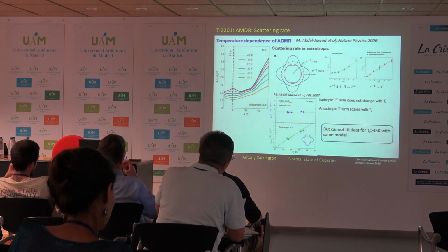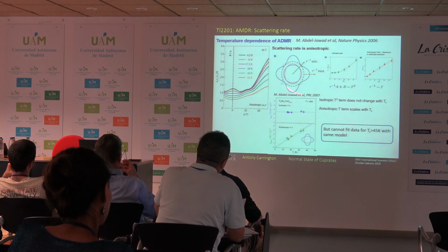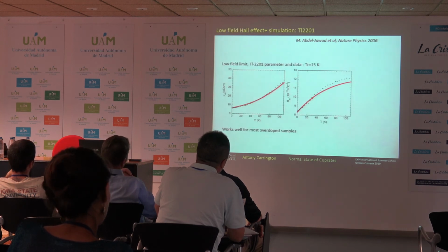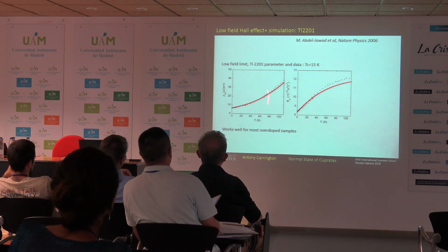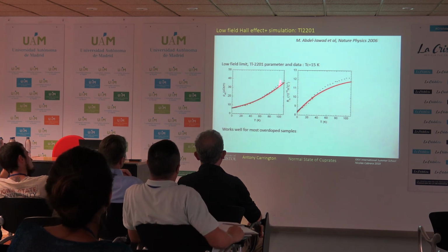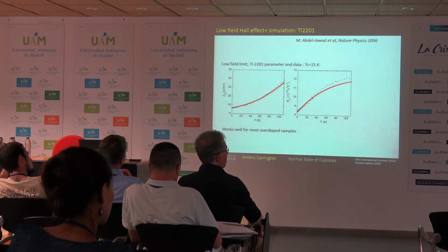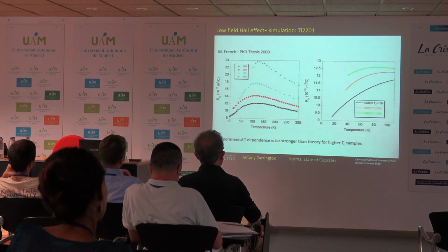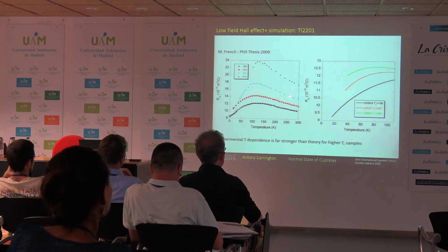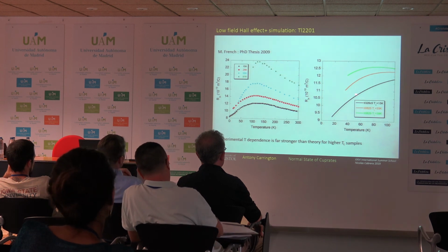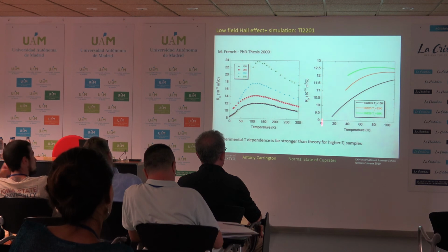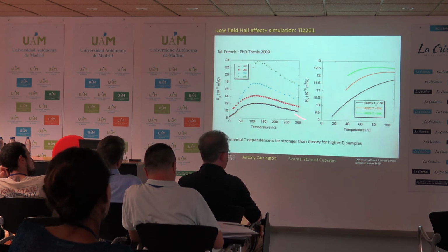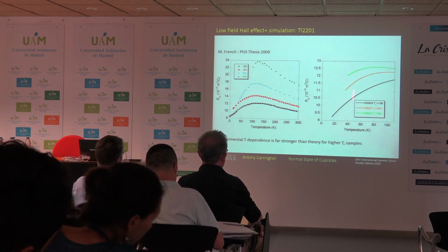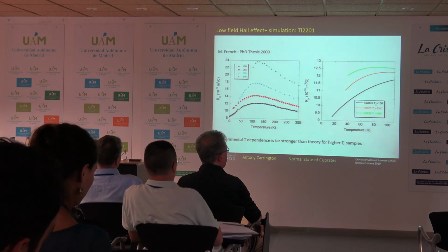Okay? Now that you know the form of the Fermi surface, the form of the scattering rate, can you explain the Hall coefficient? Answer, yes. So this is that simulation of the Hall coefficient and the in-plane resistivity using those parameters. And you can see it works pretty well. On the other hand, we should say things that don't work as well. It works very well when they're very overdoped, but when the doping gets towards optimal, it doesn't work, right? So this is what you get from the simulation. Notice the scale here. It's only varying by about 20%, whereas the real data is varying by a factor of 2. So the scattering rate anisotropy works to some extent, but it doesn't explain the whole thing.